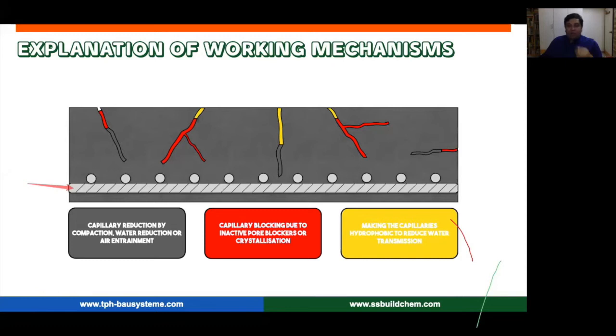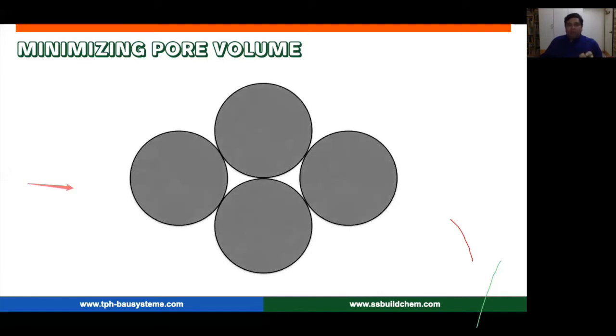And then the last one would be to add something hydrophobic to your admixture mix, so that the hydrophobicity itself treats your capillaries and does not allow water to pass through them that easily. So the aim is to finally minimize the pore volume. For example, if these are the cement particles in your mix, then what we do with the additive technology is introduce materials that are a little bit smaller than cement, mixed with materials that are still smaller than those particles, and these materials are all reactive. Once they react, they create a lot more CSH gel, and they fill in all the teeny tiny spaces between the reacted cement as well, rendering your concrete waterproof.